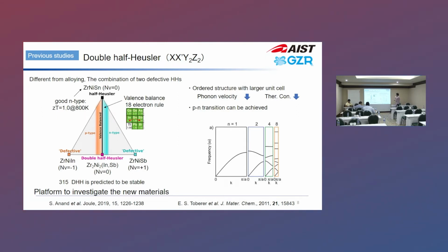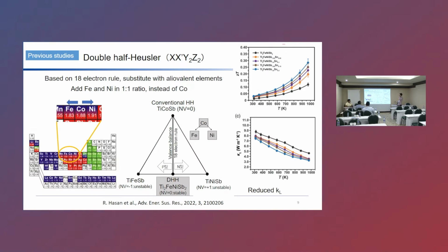One benefit of making this compound is that if it has an ordered structure, a larger unit cell, the phonon velocity can be lower, so you can have lower thermal conductivity. There is a crystallographic reason for this: you are folding the Brillouin zone and you have more optical branches, and the phonon velocity goes down as you have a larger unit cell. So if you can realize the ordered structure for double Half-Heusler, it would be nice for improving the properties.